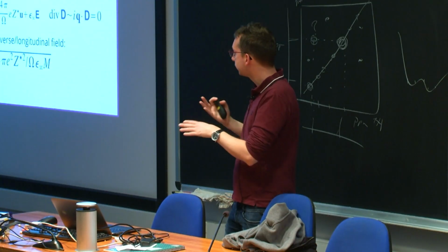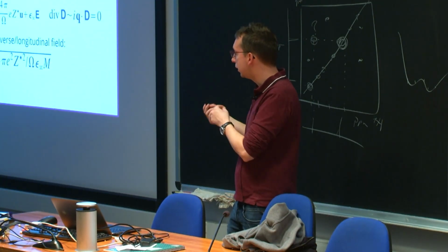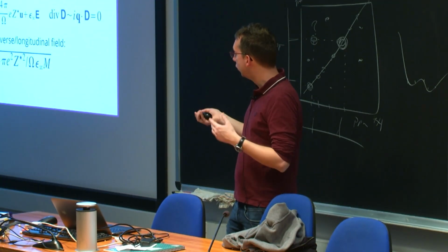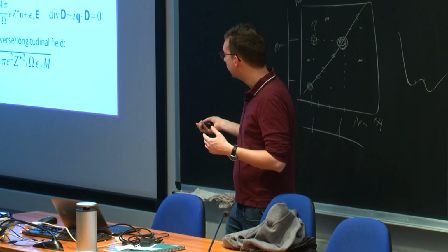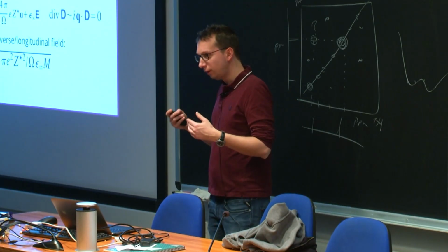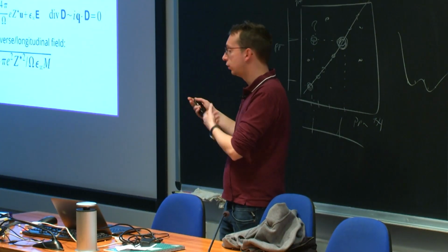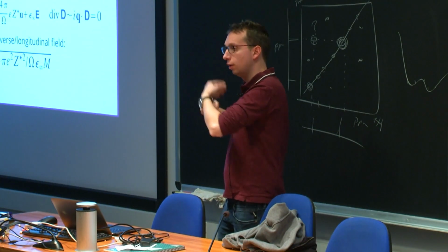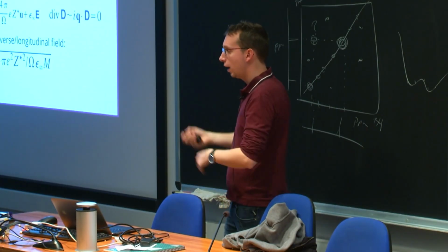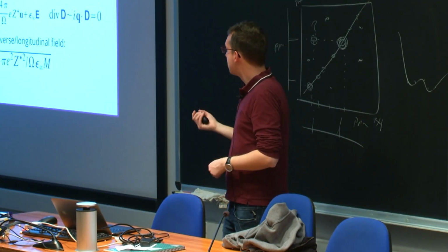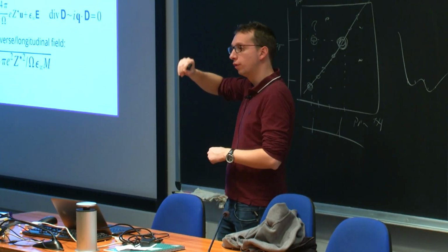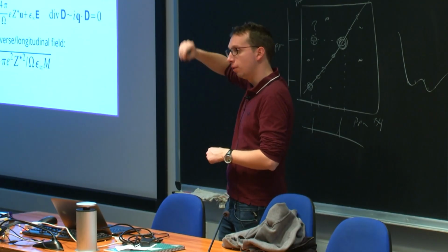Not always, but in materials which are a bit less symmetric, it happens. And so if you don't keep in account this correction, it is very difficult to do the Fourier interpolation that you saw yesterday. So you must take this term out, do Fourier interpolation, put it back in. Otherwise, you will get what happens when you do Fourier transform of a square function. You get a lot of wiggles.